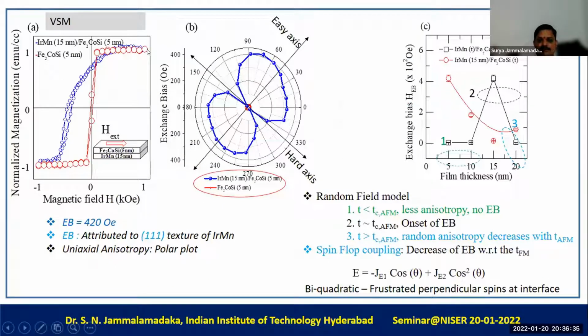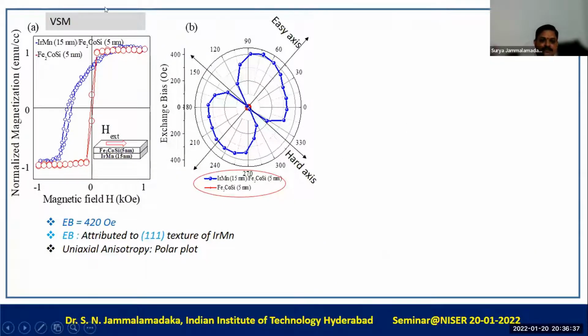So we also tried to do VSM for the single layer and for the bilayer sample. As you can see here, for a single layer, we don't see any shift of the magnetization loop. The magnetization loop is symmetric around zero. However, as soon as we deposited Fe2CoSi on top of the iridium manganese layer, we do see a shift of